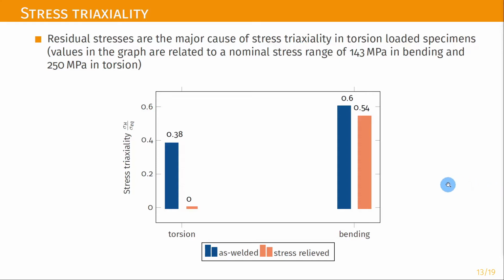One possible way of explaining the different behavior obtained in the two cases of torsion and bending was found in the hydrostatic stress. The pure torsional load does not provide, in fact, a counterblow for the hydrostatic stress, unlike the bending one. Therefore, we consider stress triaxiality as a damage factor. Four stress triaxiality factors are here presented, specifically for pure torsion and pure bending in as-welded and stress-relieved conditions.